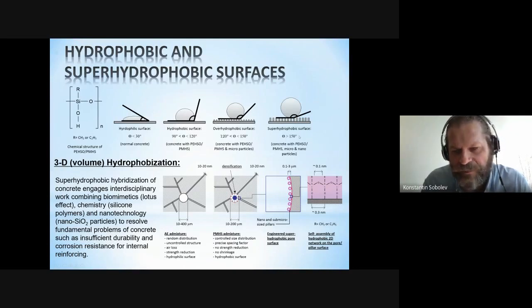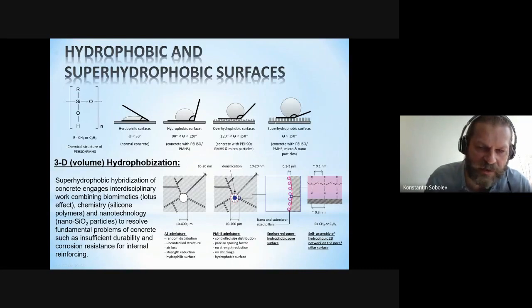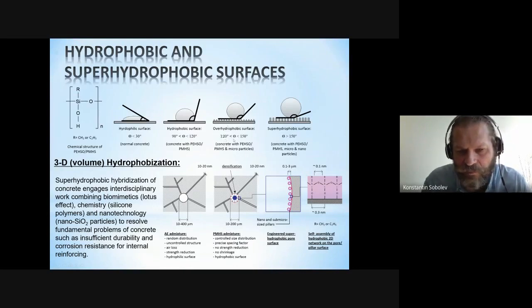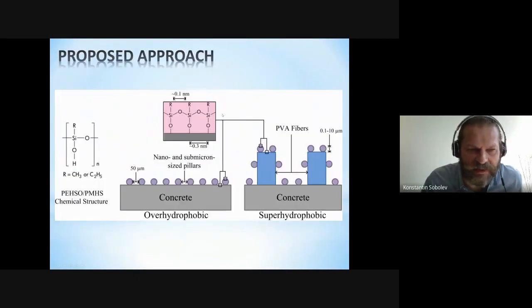A superhydrophobic surface has a contact angle of 150 and a very low roll-off angle, and this is what we usually observe on a lotus leaf. We offered a new definition, over-hydrophobic surface, between 120 and 150 degrees, and this is easily realizable in concrete. 3D volume hydrophobization can also be realized with the proposed idea.